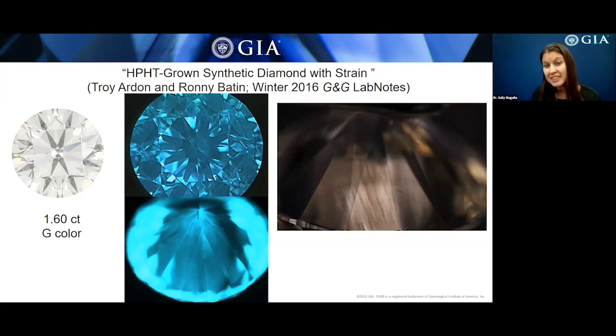And what makes this diamond interesting is that when viewed under polarized light, the HPHT grown diamond showed weak strain throughout most of the body, but one side of the pavilion displayed noticeable birefringence caused by internal strain. This is noteworthy since HPHT grown lab diamonds are known for being mostly free of strain. And the cause of the strain in this particular diamond is unknown. At the time, the authors suggested that if it was related to a new growth process, then they would expect to see more strained HPHT grown diamonds in the future. However, in the years since, we've seen less than a handful of other examples since this original lab note.